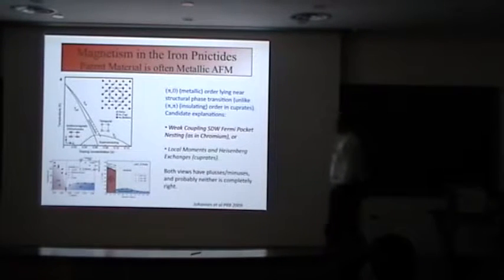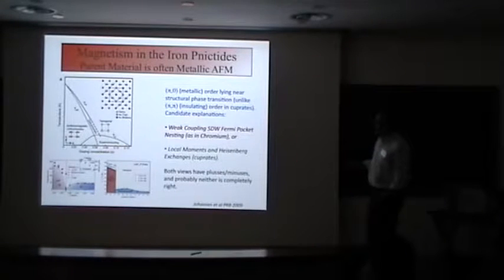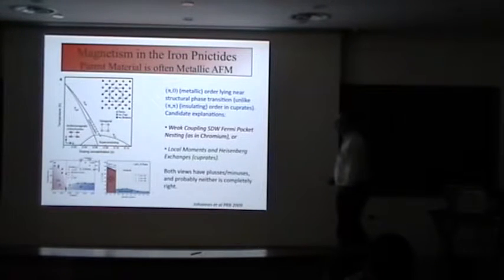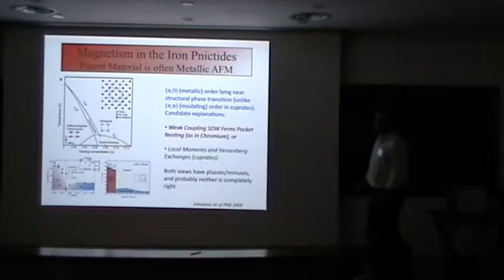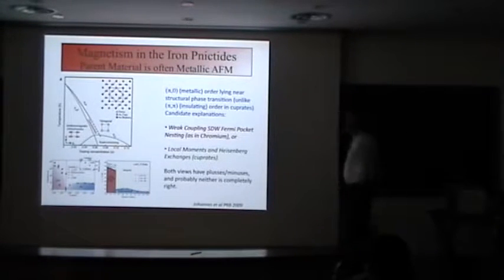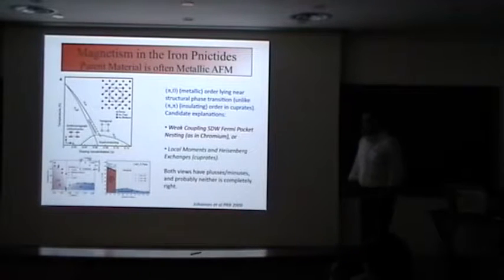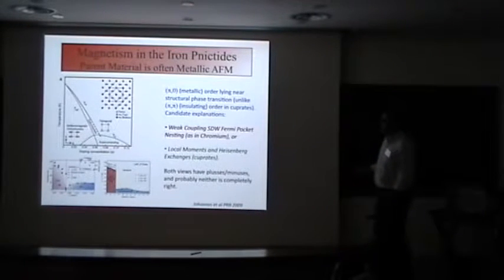Another difference with the cuprates is that there's a structural transition, as we pointed out already, that in some cases lies very close to, if not on top of, the antiferromagnetic ordering temperature in the parent compound, and then it splits with doping or stays split with doping as you move away from the parent compound. Then the orthorhombicity and magnetism give way to superconductivity, and it's very tempting...